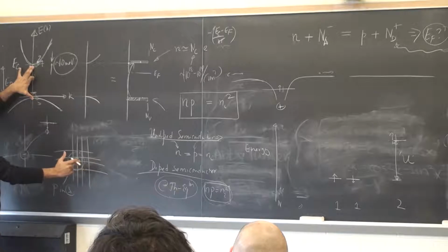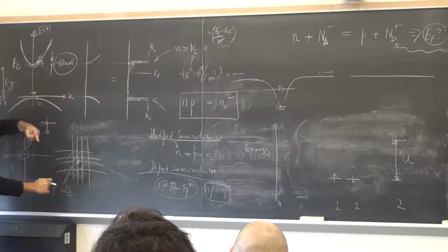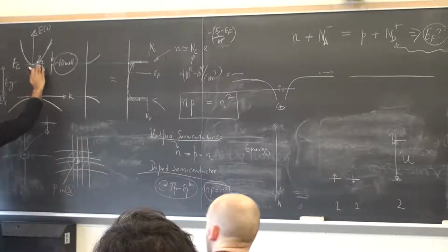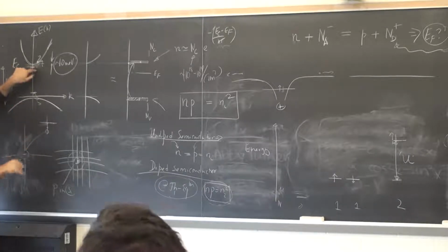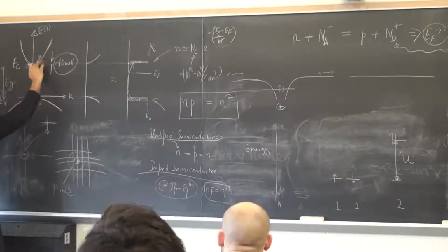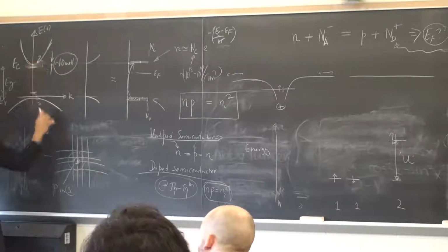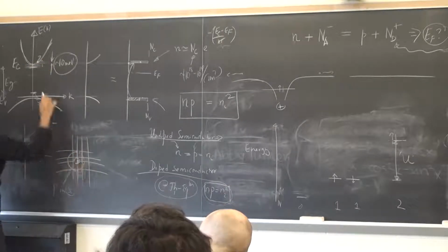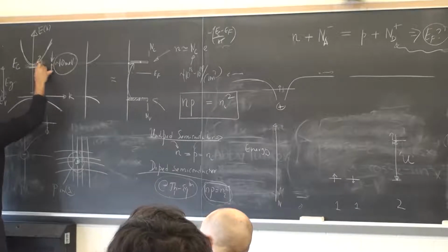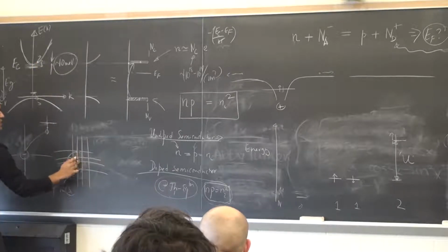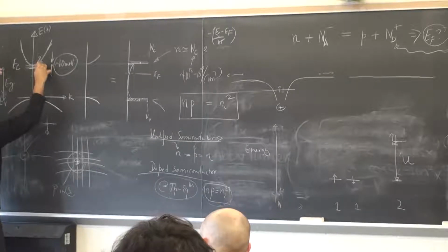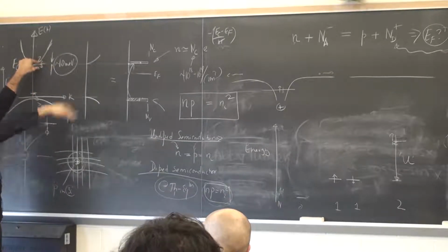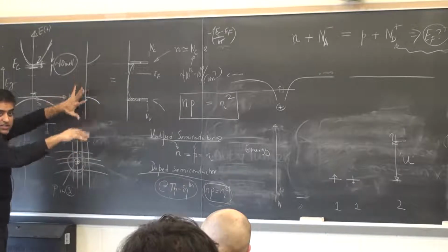But now you have one extra electron, so it must have a state somewhere, and we haven't yet accounted for it. A good donor is when that state lies just below the conduction band at that donor activation energy. So the energy from the state of the electron, if it was tied to the donor atom, to the bottom of the conduction band of the whole crystal, is the donor activation energy, the energy it takes to kick this electron into the crystal.